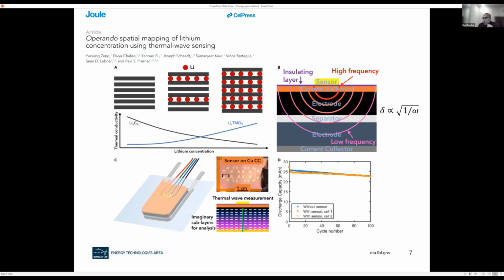the lithium concentration, right? So we use something called thermal wave sensing, which is pretty well known in thermal communities, also known as the 3 omega technique. What you do is you have a sensor here which is heating sinusoidally, okay? So you're passing a sinusoidal current, and you can do a frequency sweep.